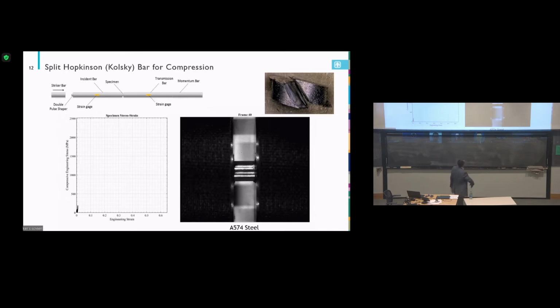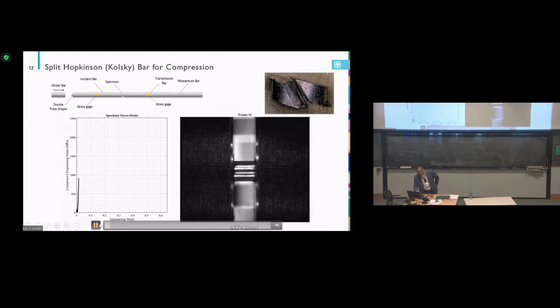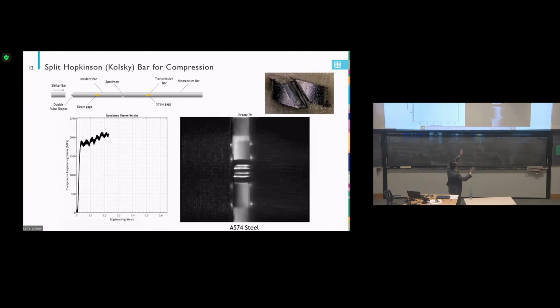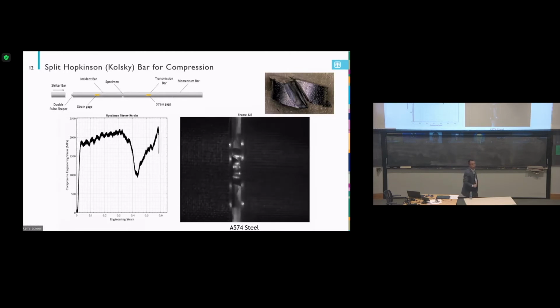During the compression test, there's the bar, and you can see in the middle, that's the specimen. Then when they hit the bar, you will see how the specimen gets compressed, a little bit of bulging because of the friction, then a shear fracture, nearly at 45 degrees, like the photo shows in the corner. So that's how we see the specimen fractured, and this is an engineering stress-strain curve that we calculated from the equations that I presented a couple of slides ago. So that's a compression test.